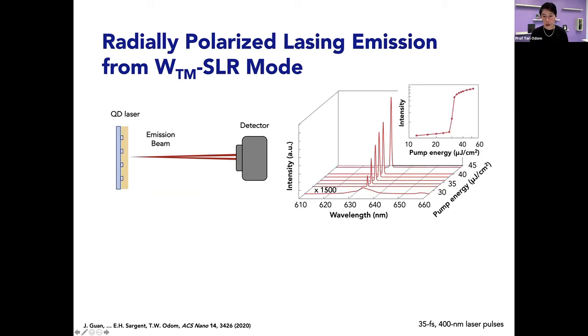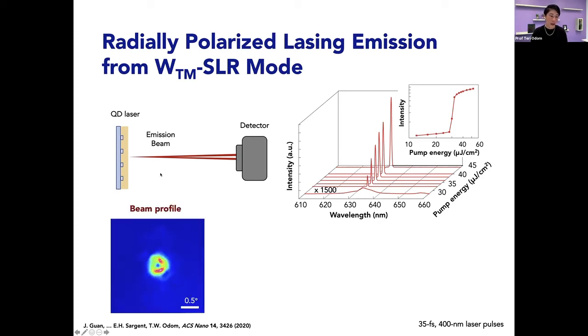And so we see first, establishing on a log-log scale, what the input-output curve looks like. And different from the dye molecules, you can see this is this characteristic S shape as you would expect for semiconductors. But it looks nice. And then when we looked at the beam profile, what the beam looks like, I mean, this sort of came out at the same time as the discovery of what a black hole looks like, even with some of the intensity differences. I mean, it was surprising to us why there was nothing in the middle, but then there was some brightness at the edges.